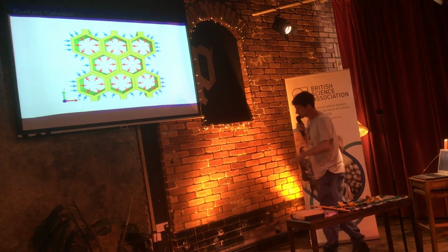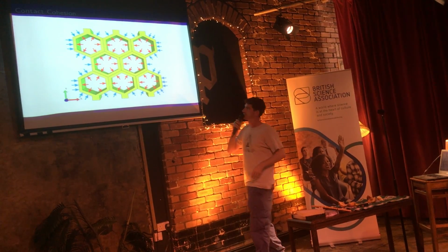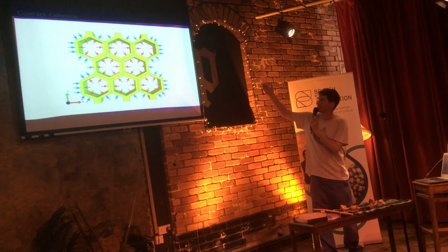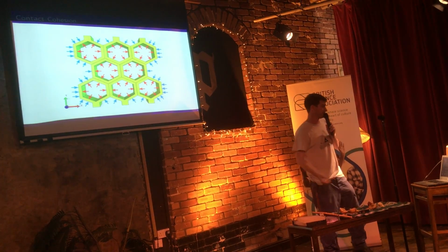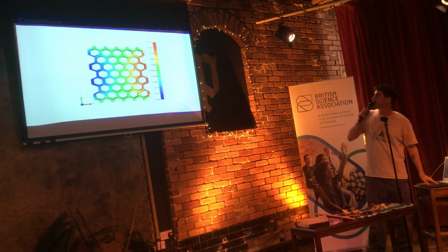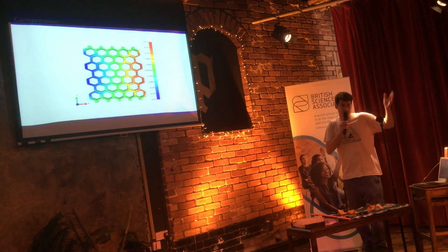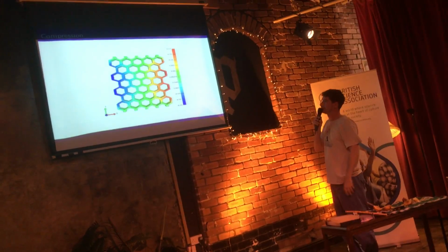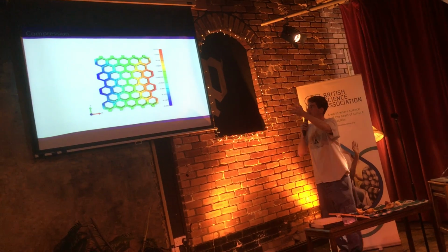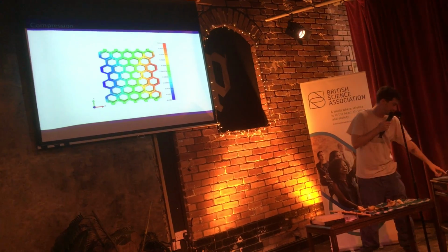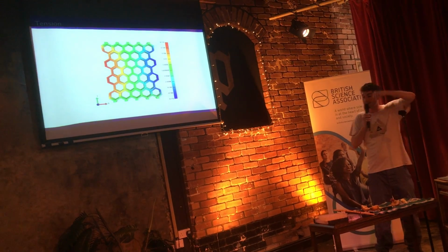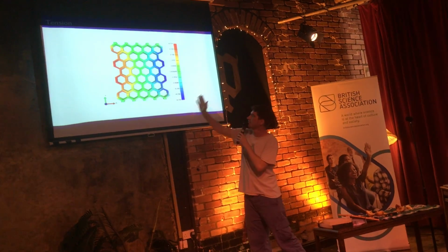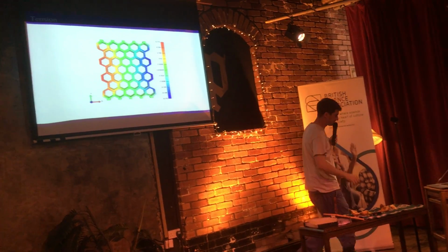Now, this is one of my structures. We've got hexagonal cells, and to simulate cohesion between the cells, some sort of stickiness, we say that there's a pressure that pushes between the cells. Now, you need to check it against the normal validation cases. So we compress the material, and yes, it acts like a honeycomb would when you compress it. And when we put it in tension, once again, it's bowing in on the sides, as you'd expect.